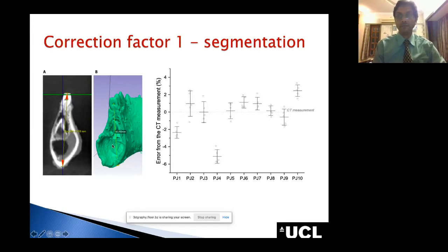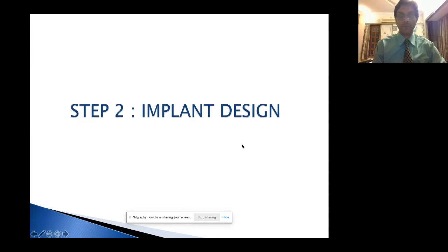So to account for this error, the measurements of the pig jaw were taken both in the 3D visualization, so in the segmented part, and in the CBCT itself. And the difference was accounted as the correction factor number 1. And that was used to scale up or scale down, in case the error was positive or negative, for the final design.